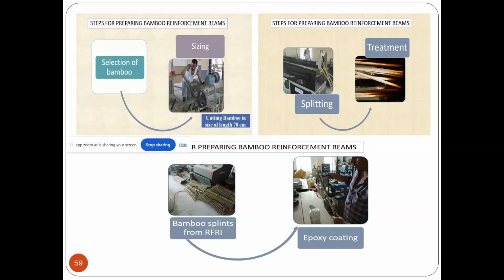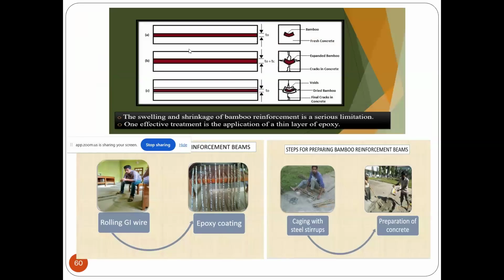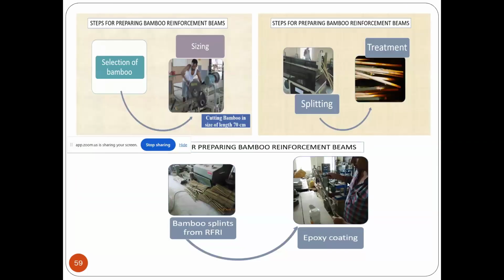Then comes the moisture-induced dimensional instability. The swelling and shrinkage of bamboo reinforcement is a serious limitation. This is the problem. First, within the concrete, the bamboo will be like that. Then, soaking the moisture from the concrete, the bamboo may expand, and while contracting, it is reducing in size, creating some gap, finally reducing the bond. In both the cases, it may split the concrete or there may be lesser bonding. To address this problem, epoxy is applied. The epoxy coating on each of the bamboo splints was done.